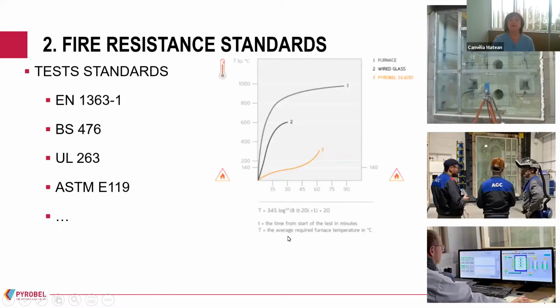How do we assess the fire-resistant glass properties? There are standards, EN, BS, UL. The glass installed in a frame, the element glass plus frame, is installed in the front of a furnace, and then a heating curve which simulates a real fire is applied to this glass. The heating curve is quite similar for all types of standards. What is a bit different is that for the UL standard, the hose stream is applied at the end of the test on the glass. The EN standard has different thermocouples to pilot the furnace, but they are quite similar.